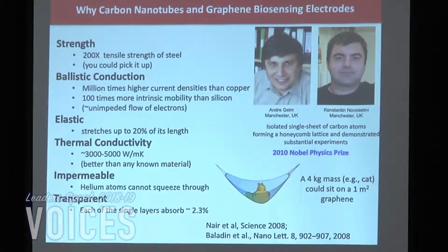It's elastic, it stretches up to 20% its length. So in theory, if you had a 4-kilogram cat sitting on a single monolayer of graphene, it could sit on a 1 meter squared sheet of that material if you could hook it up that way, which we're not quite there yet. It has the highest thermal conductivity known of any material. It's almost impermeable, so even small helium atoms can't squeeze through the carbon lattice. And it's really transparent. A single monolayer you couldn't really quite see. It doesn't absorb much light, only about 2%.